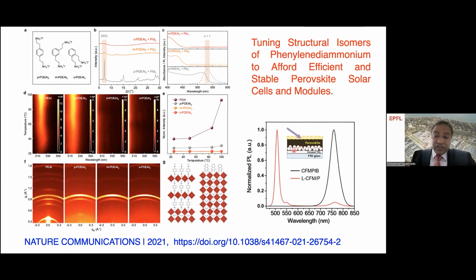And just to remind, how does the two-dimensional perovskite look? So this is the two-dimensional perovskite emission spectra. When we excite from the top side, you can see very clearly the two-dimensional perovskite emission peak. And if we don't have this two-dimensional perovskite, you can see only the three-dimensional perovskite emission.